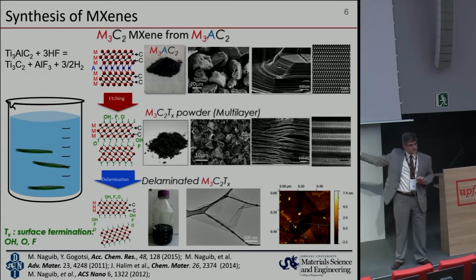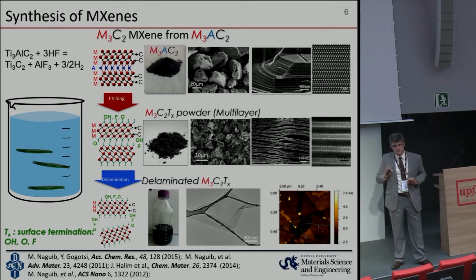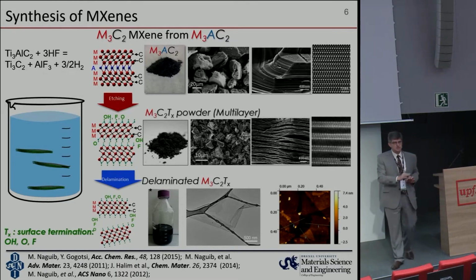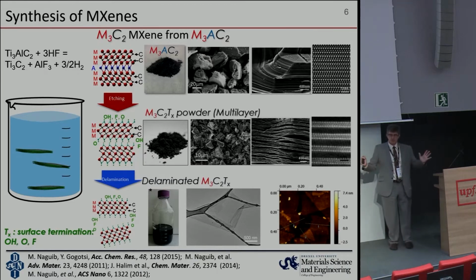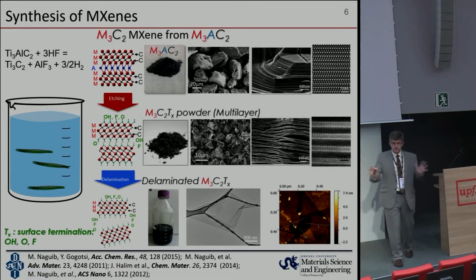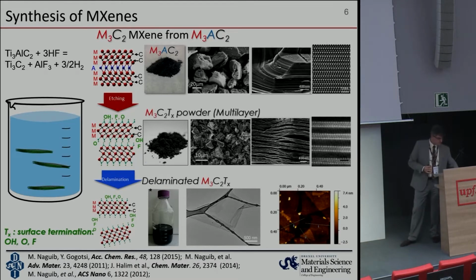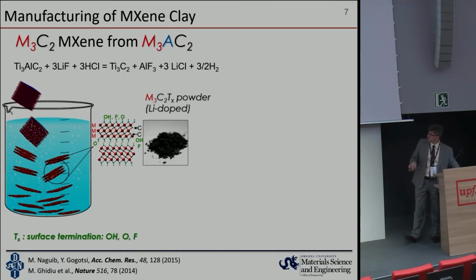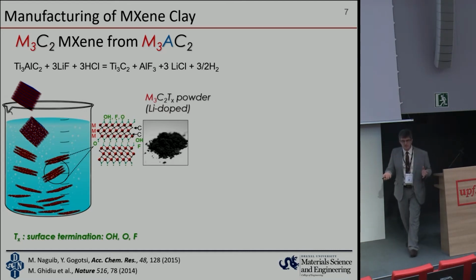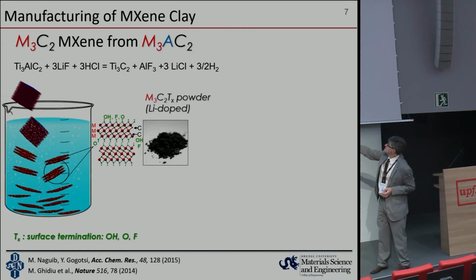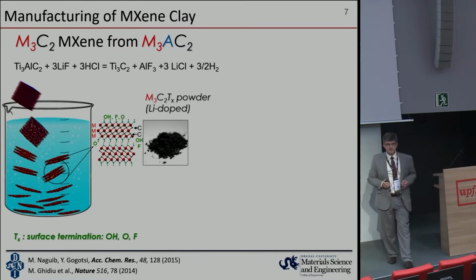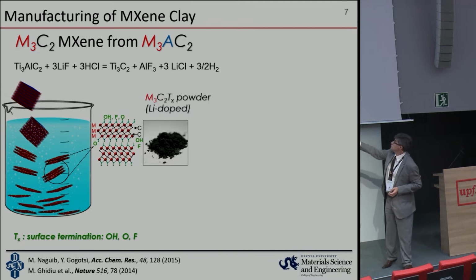And the reason why oxygen-terminated Ti3C2 MXene forms a stable colloidal solution is that there is a high negative zeta potential. For MXene, it typically ranges from -30 to -80 millivolts. So flakes stay stable in solution and don't want to stick together. Unlike graphene, just in water, they will be floating separately. Within about a year or two after discovery of the first MXenes, we showed that it's possible to get rid of HF and use benign salts like lithium fluoride or sodium fluoride, and benign acids which are cheap and non-toxic, like hydrochloric acid, to do the same etching process.